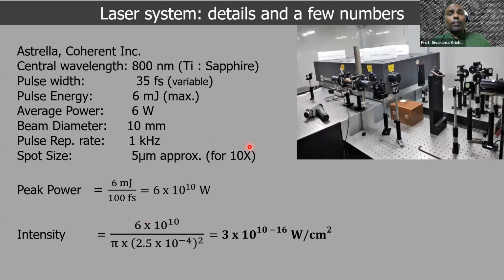Now, a few numbers which would hopefully try and convince us that these lasers are ideally suited for the kind of work that we are going to showcase here. This black box right at the behind is the laser system. It is an Astrella laser from Coherent, an American laser vendor. This is a typical titanium sapphire femtosecond laser with the shortest pulses being 35 femtoseconds, but we tend to use longer pulses as such. Each of these pulses can have a maximum energy of 6 millijoules. It sounds rather small, but I'll hopefully convince you that this is more than sufficient.